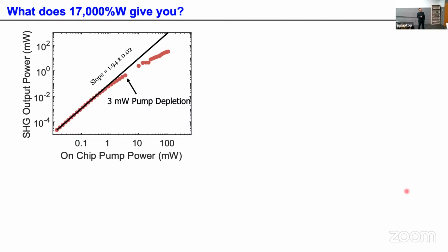So here's a typical light-in light-out curve. You plot the pump light, and this is the second harmonic generation. In the low power regime, you have a really quadratic dependence of the second harmonic on the fundamental mode. But when your power becomes large enough, you deviate from this quadratic dependence. The deviation happens because your fundamental mode is coupled so strongly with the second harmonic. The fundamental mode 1F and 2F start to hybridize, and you form a new set of super modes.